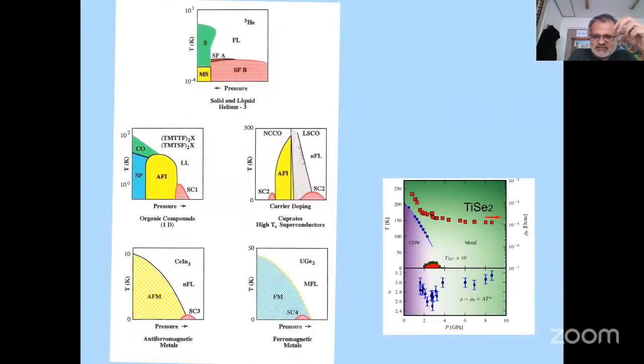So I'll jump through again, establishing this idea of tuning an ordered state and leading towards new quantum states, particularly superconductivity. When we started, it was only really understood in terms of heavy fermion systems and possibly high TC materials. But with a little bit of imagination, we can see it's quite general, happens across different things, including solid or liquid helium, intermetallic systems, organic systems, of course, oxide systems. But it's not limited only to magnetic systems; we can see that happening also potentially in charge density waves, so that's the initial title of spin and charge type of systems. And we will understand this through the results we have obtained.